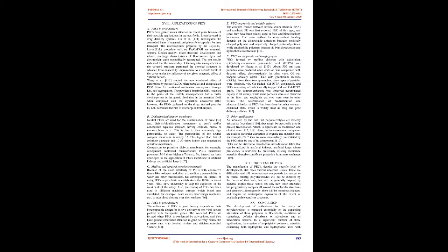De Vasconcelos et al. 78 studied the effect of the molecular weight of polymethacrylic acid, PMAA, on the formation of PECs based on chitosan. They reported an increase in solubility of the complexes as a function of the molecular weight of PMAA, which may be due to the lower presence of carboxylic groups at the outer parts of PMAA coils due to an increase in molecular weight.